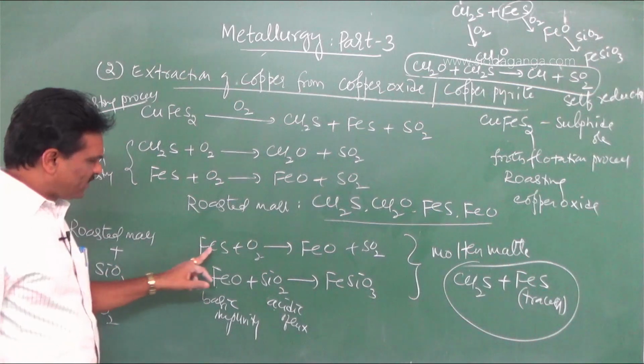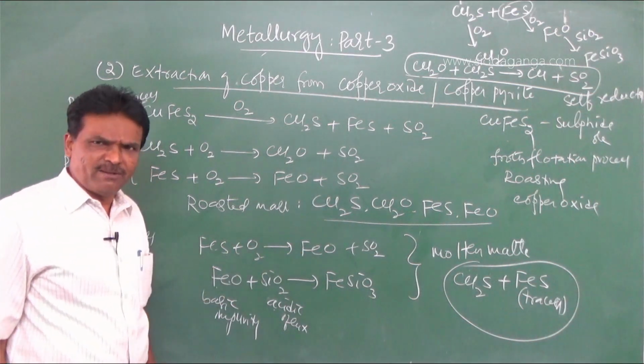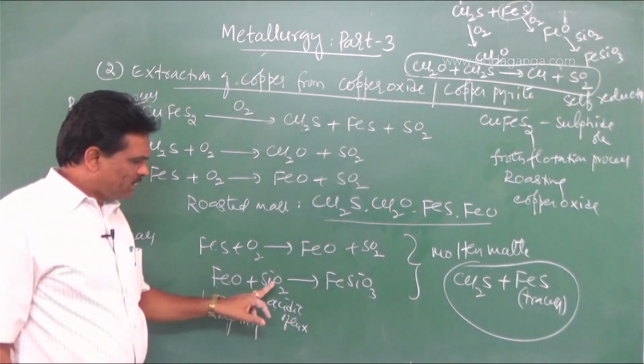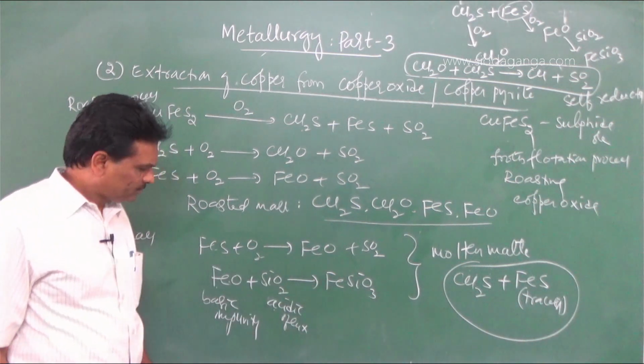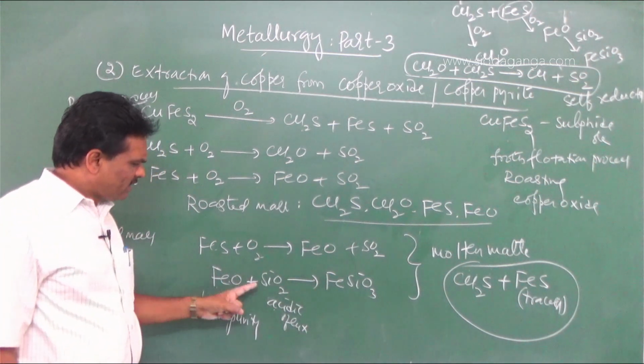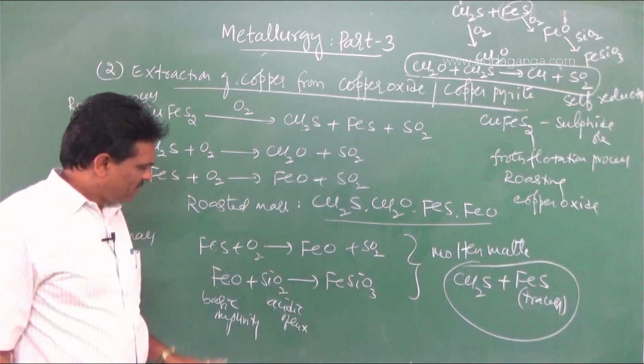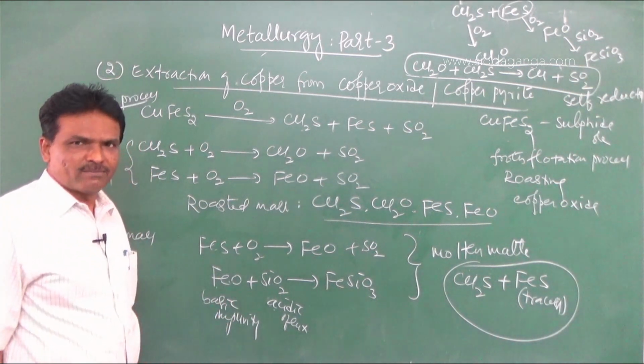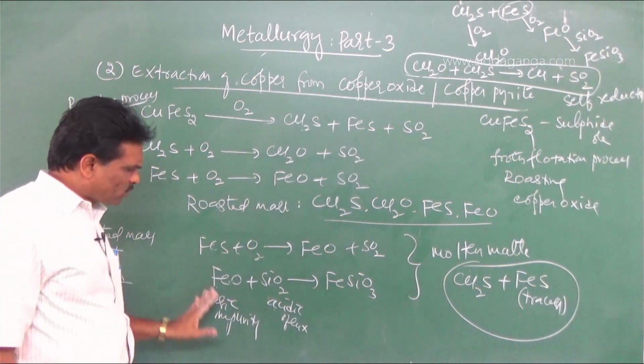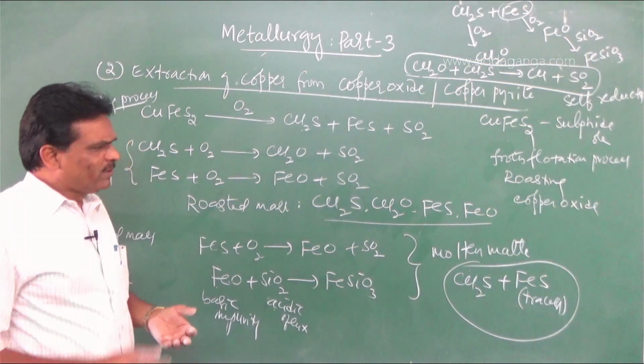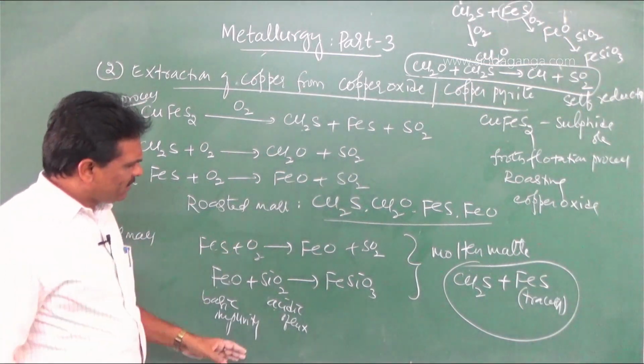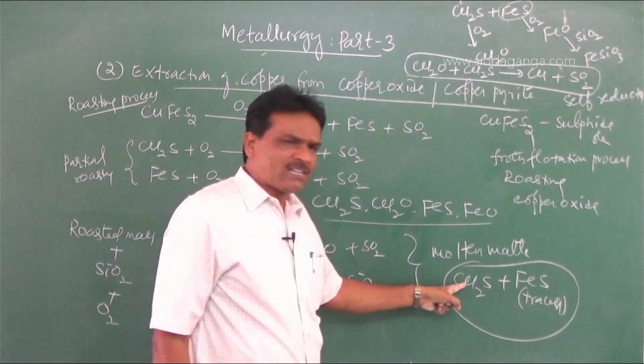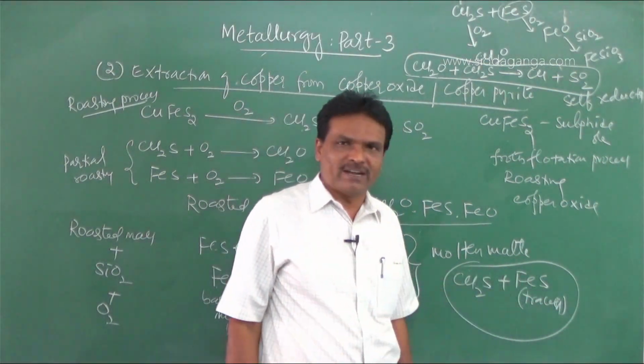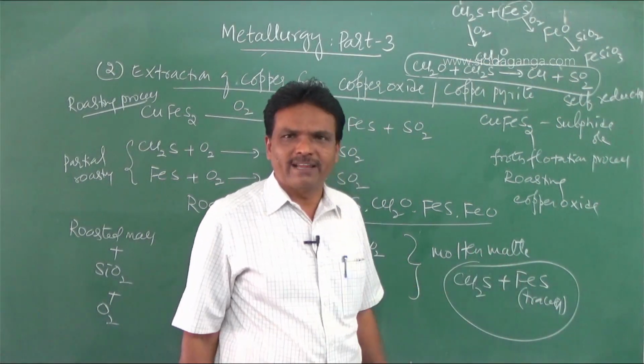During this process, ferrous sulfide is partly oxidized to ferrous oxide. Ferrous oxide combines with silica to form ferrosilicate slag. So here silica acts as acidic flux, ferrous oxide is the basic impurity. So therefore in this process we get a molten matte. What remains is cuprous sulfide and traces of ferrous sulfide. This is called molten matte.